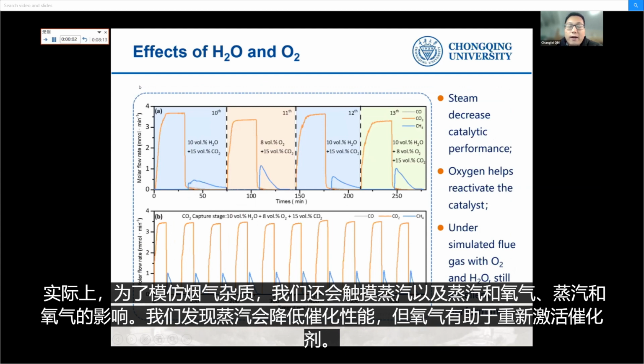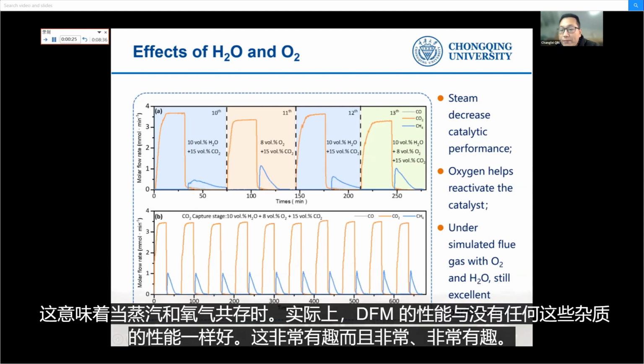To mimic the flue gas impurities, we also tested the effect of steam and oxygen. We found steam decreases catalytic performance, but oxygen helps reactivate the catalyst. It means when steam and oxygen coexist, the performance of the DFM is as good as that without any of these impurities. This is very interesting.